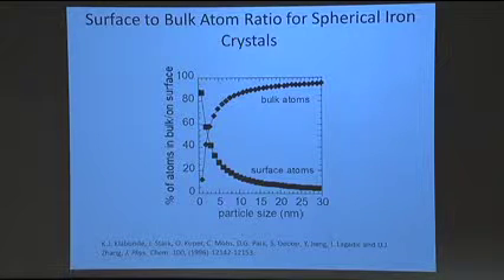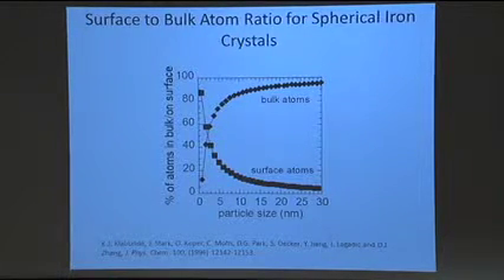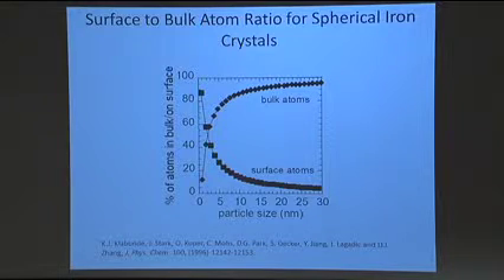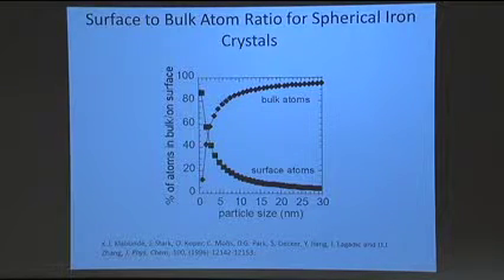And you can see here, when I start to get below about 10 nanometers, this ratio changes dramatically, okay? And why this is important, as I said, is because the surface atoms have a lower coordination. They have more free dangling bonds. Their physical, thermal, and mechanical properties change relative to the bulk material. And as I do this, the particles start behaving more like the surface atoms than the bulk atoms when they're larger here.